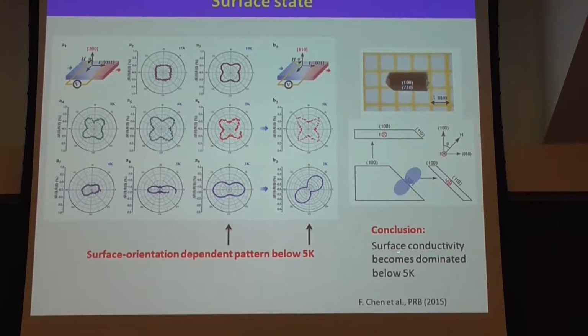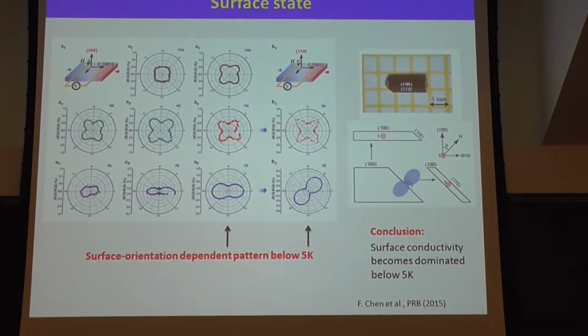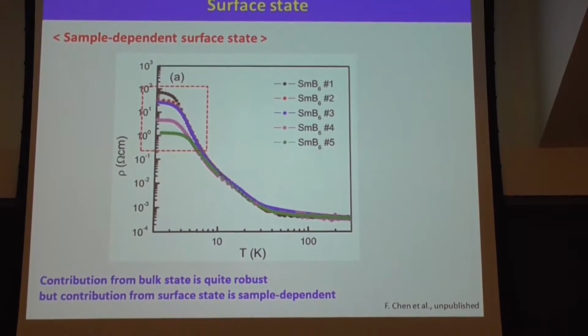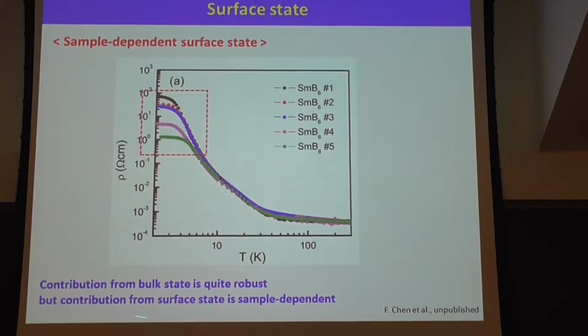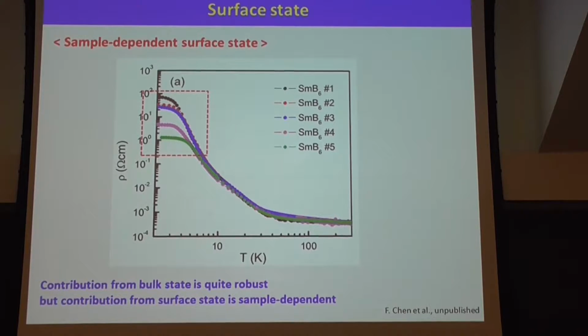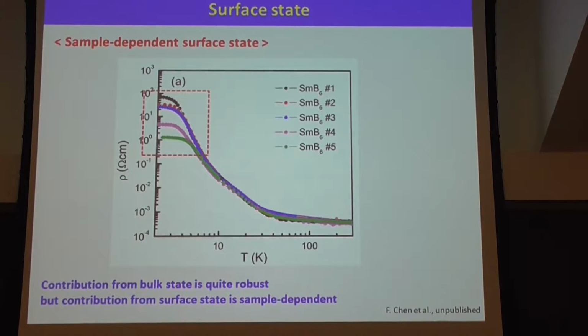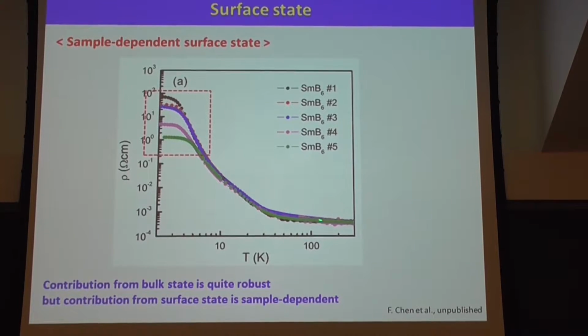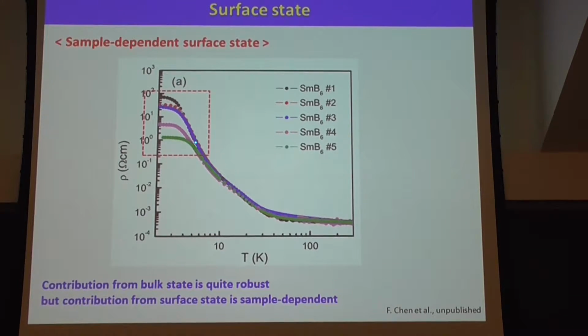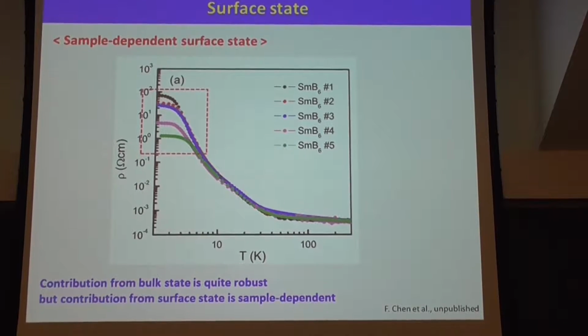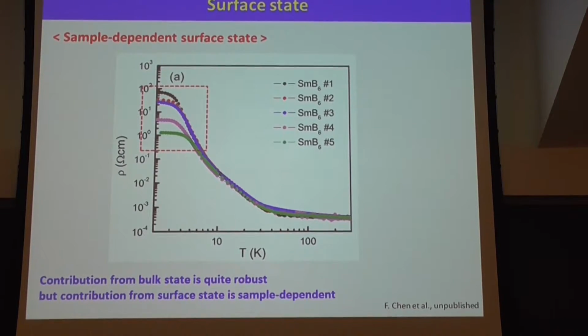The conclusion is that surface conduction becomes dominant below 5 Kelvin due to the surface state. And it's also a sample-dependent surface state. You can see our group has grown so many single crystals, and you can measure these samples. It's very interesting that for all the samples above 5 Kelvin, the data is always robust. Just below 5 Kelvin, the data is divergent. This means the contribution from the bulk state is quite robust, but the contribution from the surface state is sample dependent. This surface state conduction is very dependent on the sample.